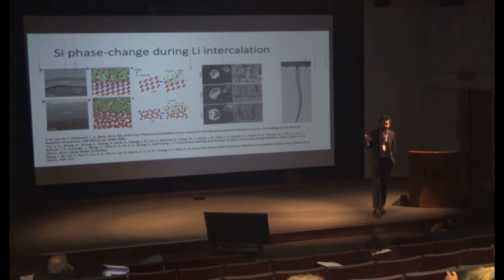When we came in, people understood a few things. First, as you put in the lithium, this phase change in the crystalline silicon or germanium is sharp. If you look at the image on the right, you see that in a few nanometers you go from crystalline to amorphous structure.